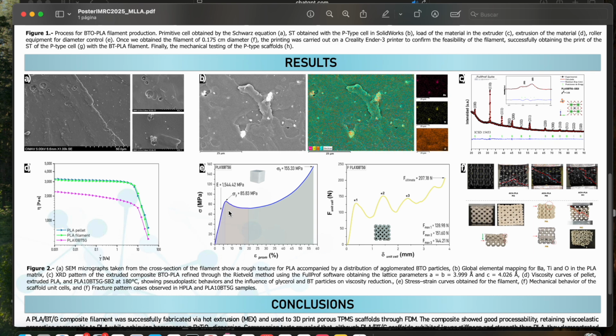The rheology results explain why the filament prints reliably at modest temperatures. At 180 degrees Celsius, the pellet, neat PLA, and composite curves all exhibit pseudoplastic behavior, and the combination of glycerin and BT lowers the apparent viscosity relative to the extruded PLA baseline. This reduction widens the processing window, improves interlayer wetting, and allows stable deposition of thin TPMS struts without stringing.